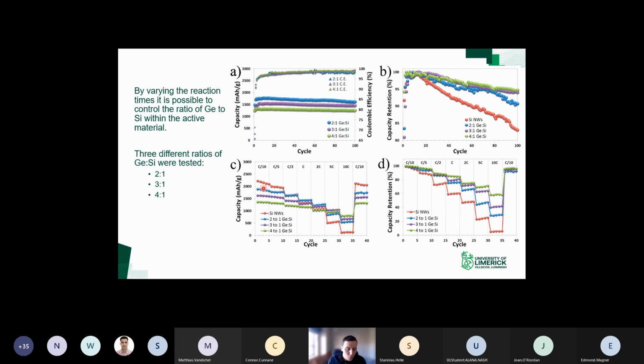So we were able to tailor then, basically, by changing the ratios of germanium to silicon. You can tailor either for high capacity. So if you want high capacity material, you increase the amount of silicon that's in there, or you can tailor it for high rate capability. So if you want high rate capability, you increase the amount of germanium in there. And that's important, it gives you a material now that you can tune.